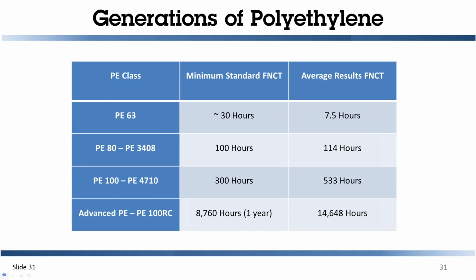On the left here, we have different PE classes. PE63 is a very old PE. We'll look at PE 3408 and 4710. Those are commonly available in the US for water applications. In the middle column, we have a minimum standard for that full notch creep test, 100 hours and 300 hours. The average result for a bunch of different testing was over those 100 and 300 hours.